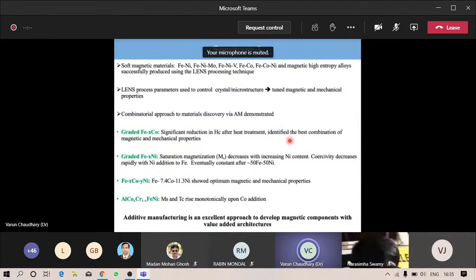In the case of iron-nickel, the saturation magnetization decreases with nickel content, and the coercivity also decreased with the nickel addition. For the ternary system iron, cobalt, nickel, we identified Fe 7.4, Co 11.3, Ni, which shows optimum magnetic and mechanical properties. For the high entropy alloy, saturation magnetization and Curie temperature rise monotonically with cobalt addition. So additive manufacturing is an excellent approach to develop a magnetic component with value-added architecture.